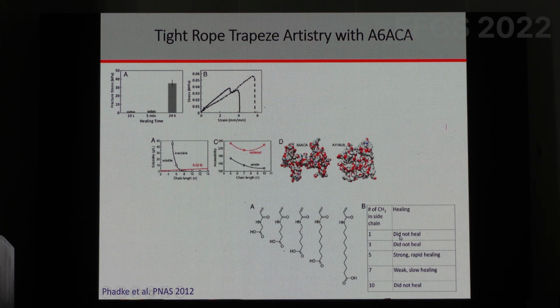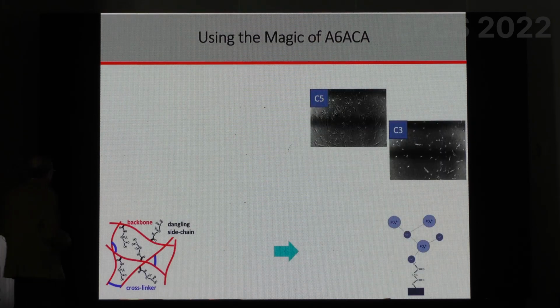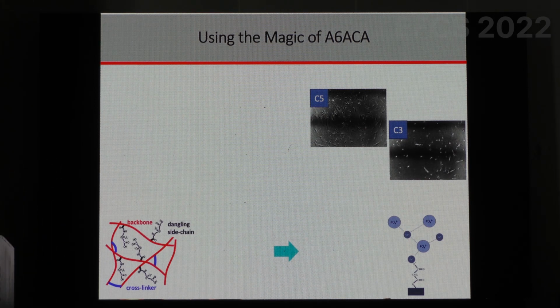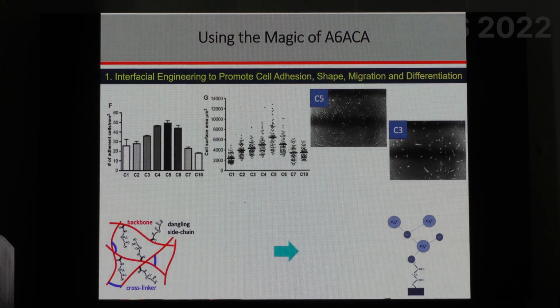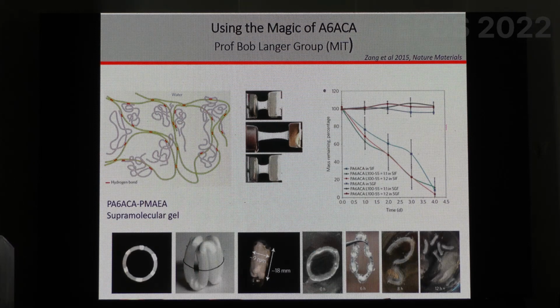Too few hydrophobic groups, the gels do not heal. Too many hydrophobic groups, they do not heal. It's just the right balance between the two that the healing happens, and the healing is quite spectacular. Okay, and this material, we've done lots of other things with it. You can grow cells on this material. It's very biocompatible, and if you have too much hydrophobicity, the cells don't grow, and they just stay there. They're small cells. If the hydrophobicity is exactly the right size, the cells beautifully spread and they adhere very nicely on these substrates. Okay, skip some of that.